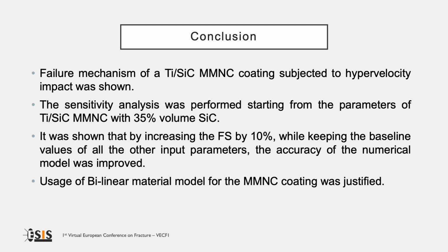The conclusions of the work are reported in this slide. The failure mechanism of a titanium silicon carbide metal matrix nanocomposite coating subjected to hypervelocity impact was shown. The sensitivity analysis was performed starting from the parameters of the titanium silicon carbide metal matrix nanocomposite coating with 35% volume silicon carbide. It was shown that by increasing the failure strain by 10% while keeping constant all the other input parameters, the accuracy of the numerical model was improved. And finally, the usage of a bilinear material model for the metal matrix nanocomposite coating was justified.